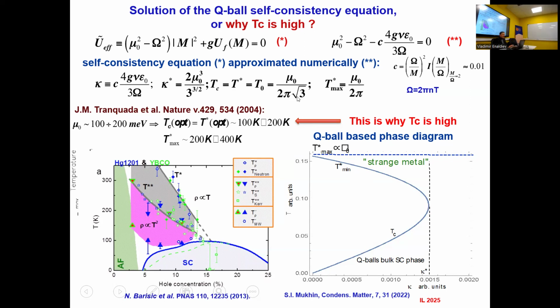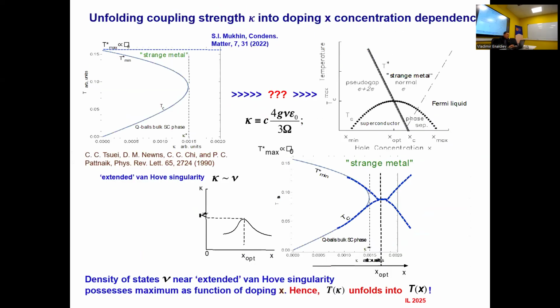So it's just defined by the inverse correlation length of the fluctuations, either of charge or spin, that are involved in Cooper pairing. Now, not much time is left. Okay, now this plot here on the left, as we have seen, shows temperatures at which there are solutions of self-consistency equations. But you may ask, okay, this is the phase diagram, and when you go with doping, it looks like that. Why here do we have only half of it?